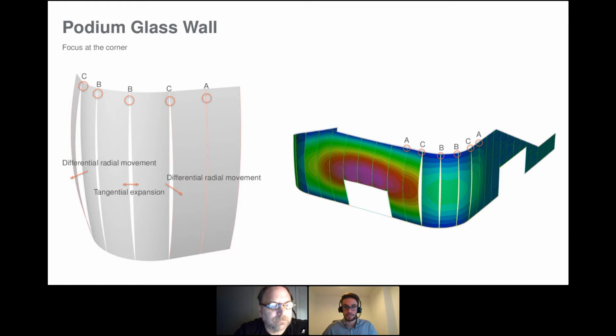The typical one, A, is like the ideal one. We have two flat panels that will tend to move in exactly the same way. When we go between curved and flat panel, because of the geometry and the different stiffness, the flat panel will tend to move much more from an out of plane point of view. Therefore, we will have some differential radial movements. When we move to curved to curved, the two curved panels, because of the geometry, will tend to move in different directions. So even if in absolute value the movement is the same, they will tend to go apart from each other. So we will experience some tangential expansion.